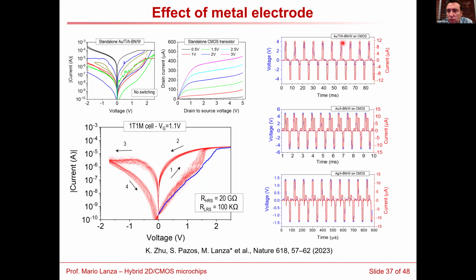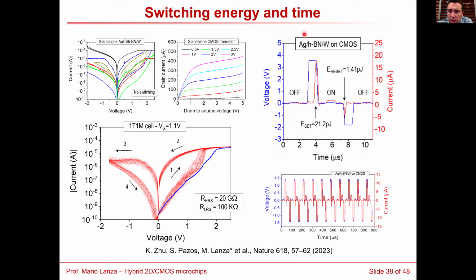For 3 different types of electrodes, we have 3 different switching voltages. Here, we need to apply almost 4 volts. Here, almost 5.5. But for silver, we have switching that is at almost CMOS compatible voltages. And actually, for this type of electrode, we also observe quite decent switching energy and switching time. It's not world record, but it's quite decent. For a first approach with this technology, I think it's a good indication.